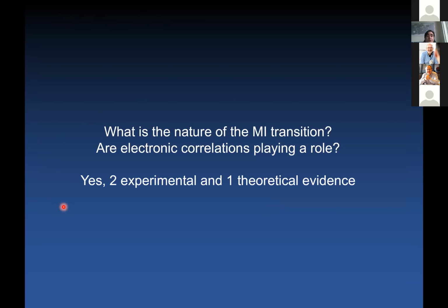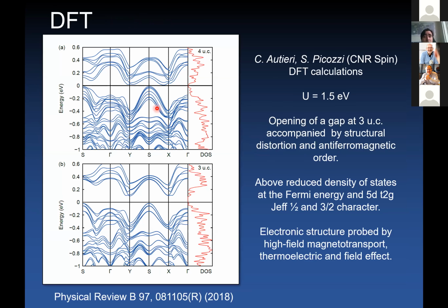So on the theoretical side, we collaborated very strongly with the group of Picozzi at CNR Spin, with Autieri. They performed a lot of DFT studies in this system, and were able to show very systematically that as a function of thickness, strontium titanate, strontium iridate heterostructures display a metal-insulator transition. And in order to observe this transition, it is fundamental to have a U of at least 1.5 electron volt, and it's important to allow for the system to have both structural distortions and antiferromagnetic order.